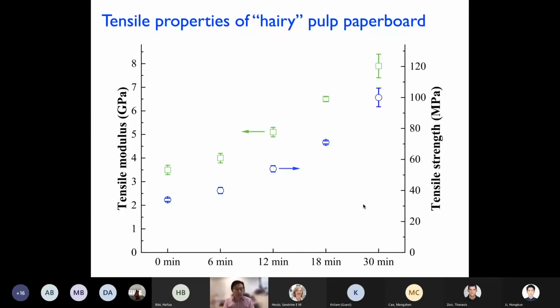The mechanical performance of these materials, again, scales beautifully with the refining time. So the green hollow icons represent the tensile modulus on the left y-axis. The blue dots represent the tensile strength on the right y-axis here. So with increasing refining time, you actually increase the modulus and strength of the final paperboard beyond conventional polymers. Even PLA has a modulus of only 3 gigapascal and a strength of about 70 megapascal, and we are able to produce something that is comparable or even exceeds that.